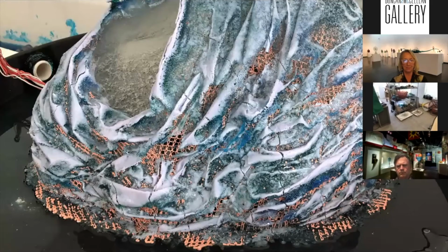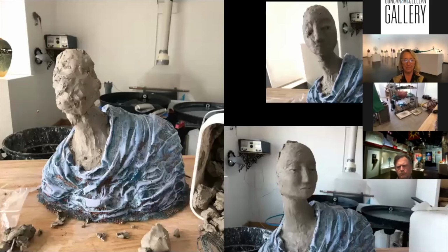And this is what it looks like when it comes out of the electroplater. The copper mesh has built up on the edges, but it's also built up in the glass, which is why I have the structural integrity that I need. This copper mesh that I have now is not the initial copper mesh that I found. This is a thicker mesh, so it holds up much better in the firings and has enough sustenance to it that I can plate it afterwards and it will build up. So that is not a pretty picture.